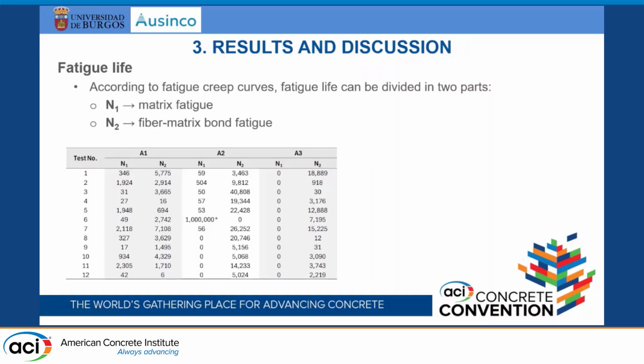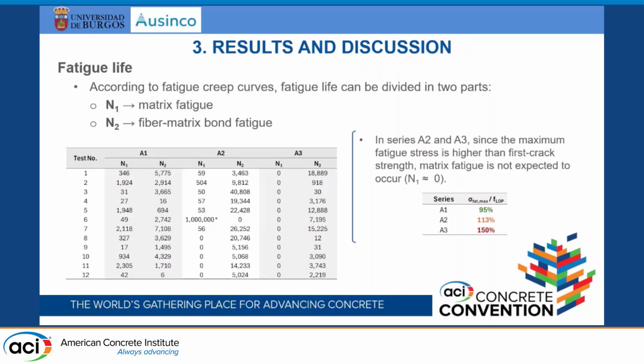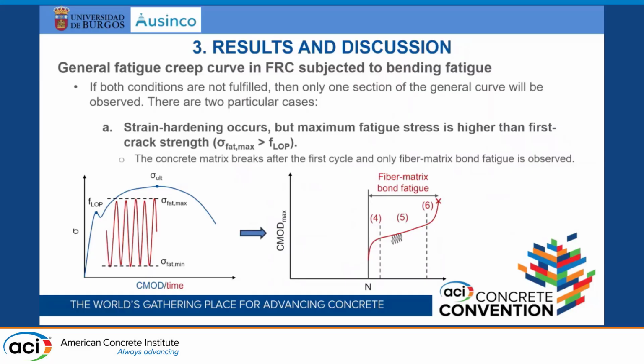And what we see is that only in A1 we have a certain amount of matrix fatigue, but matrix fatigue just disappears as we move on to A3. Why? Well, because as we move on to A3, the maximum fatigue stress is clearly higher than the first crack strength. So what's happening here, for example, in the A3 series, is that during the first cycle the matrix cracks, and we only see the second part. That is what is happening in A3 and A2. So we only see fiber-matrix bond fatigue.